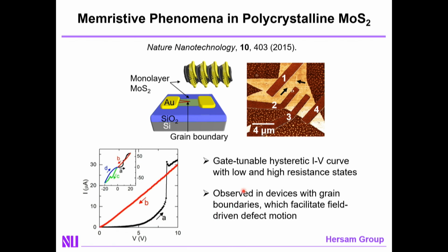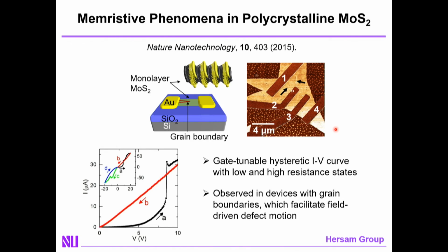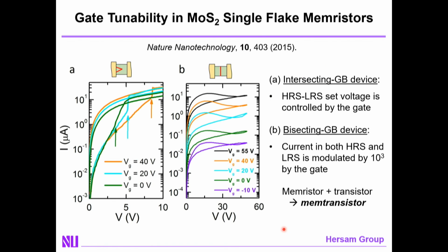It turns out, if you look at this in detail, the reason this occurs is that defects in the MoS2, such as sulfur vacancies, are being driven by the lateral field. Those sulfur vacancies are also dopants in the material, and if you reconfigure the doping profile in the channel, you'll reconfigure the resulting current voltage curve. Those defects have their motion mediated by the grain boundaries, and that's why it's necessary to have polycrystalline MoS2 to achieve the strongest memristive response.